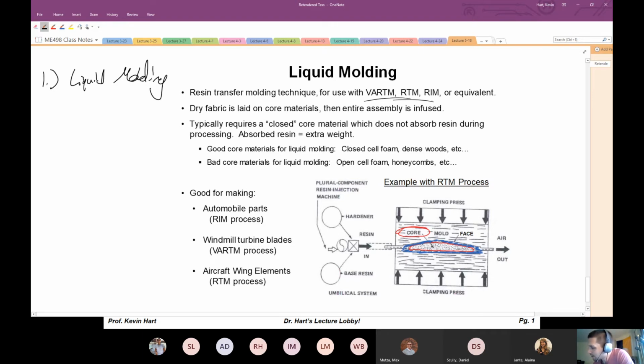Usually used for VARTM, RTM, resin injection molding. So you're moving liquid through your mold across the fibers, which are laid across a core material. All right, so dry fabric laid on core materials, then the entire assembly is infused, just like what you see here. So unlike honeycomb structure, if you try this with honeycomb, then your core would just fill up with the resin. All right, so you need your core to be a closed cell structure. So it requires a closed core material.